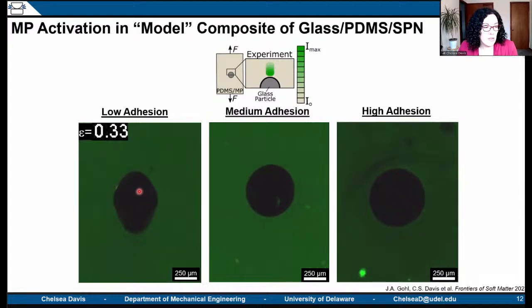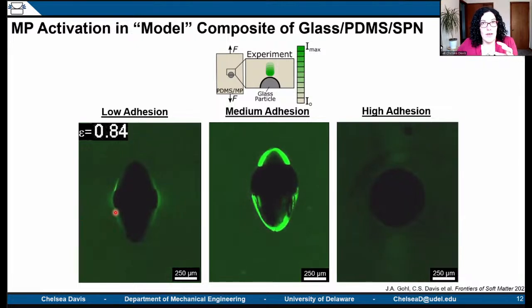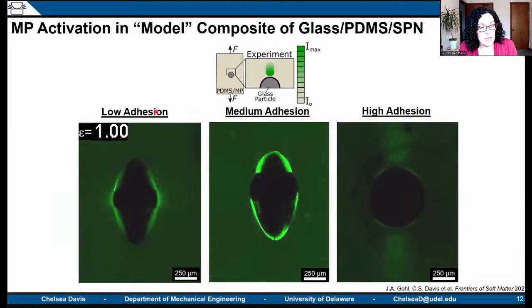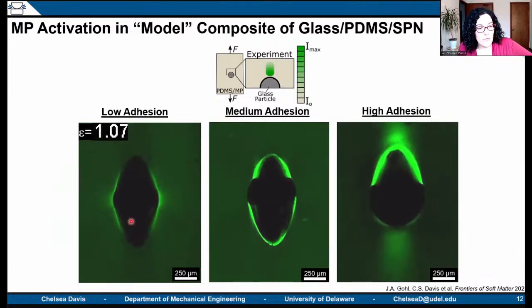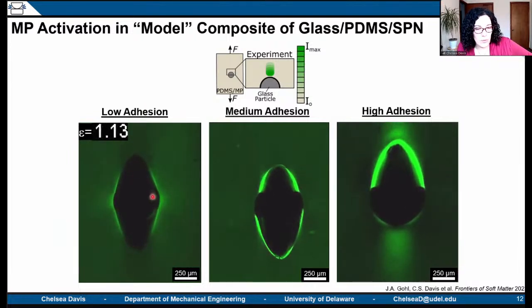And here in the low adhesion case, the sphere acts as sort of a void in our sample because there's no real crosstalk or interaction across the interface. And you can see the mechanophore starts to light up at the poles where the particle is preventing the hole from adopting the full ellipsoidal grain of rice void structure that it wants.